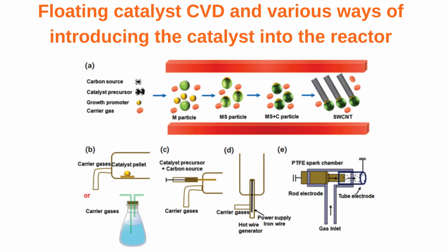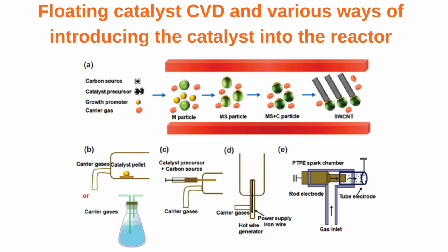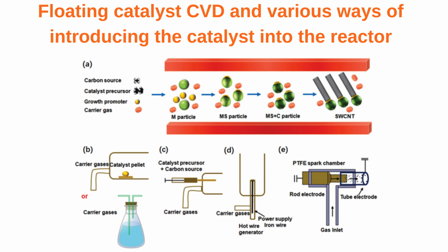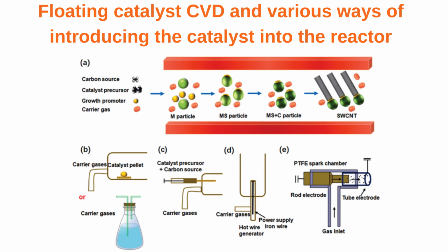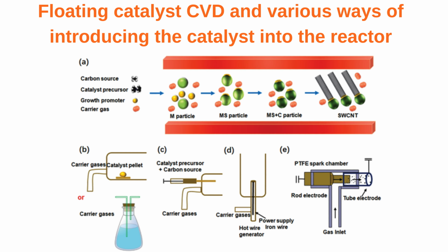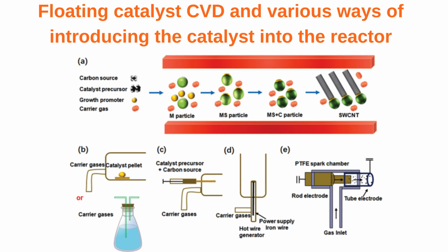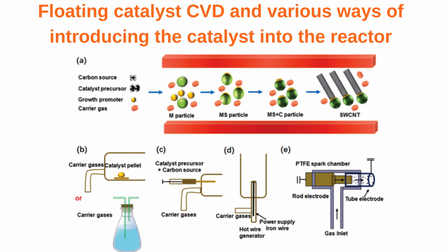A catalyst is generally not needed for MWCNT synthesis, but is needed to make SWCNTs, since the size and composition of the catalyst determines the initial stages of CNT growth, which determines the diameter and chirality of the final nanotube. The overwhelming prevalence of CVD can be attributed to advantages associated with it, such as scalability, industrial maturity of the technique, and adaptability and flexibility through the form factor of the reactor.